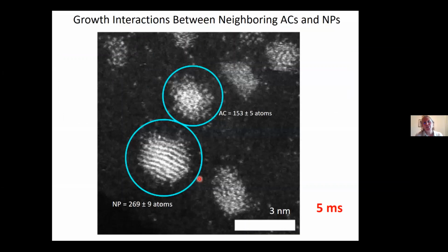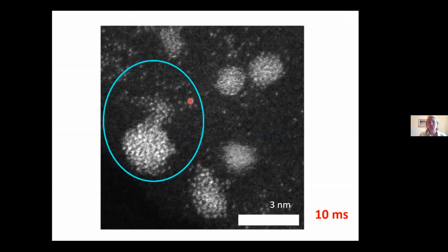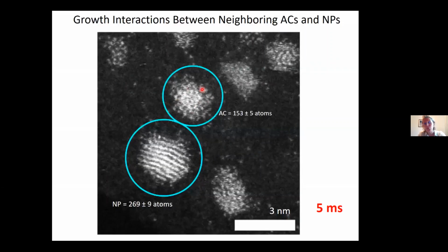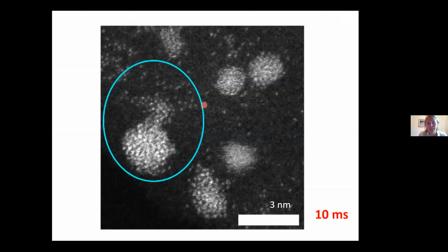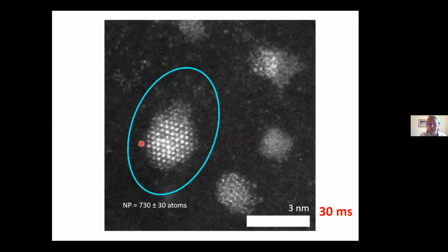So these images here are actually my favorite. Here you have a nanoparticle and an amorphous cluster, okay? And you can see these two are quite closely spaced. This is at 5 milliseconds. We've counted the atoms. If you then go to 10 milliseconds, you can see that amorphous cluster has decided that the way it's going to become stable is to give all of its atoms over to this nanoparticle. It's basically disintegrating itself and feeding into that neighboring nanoparticle until that neighboring nanoparticle itself turns into a crystalline nanoparticle. And you start to see a beautiful cleanup of the atoms around that particle.